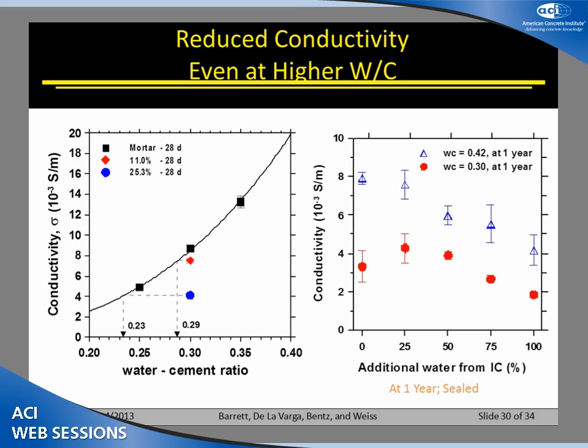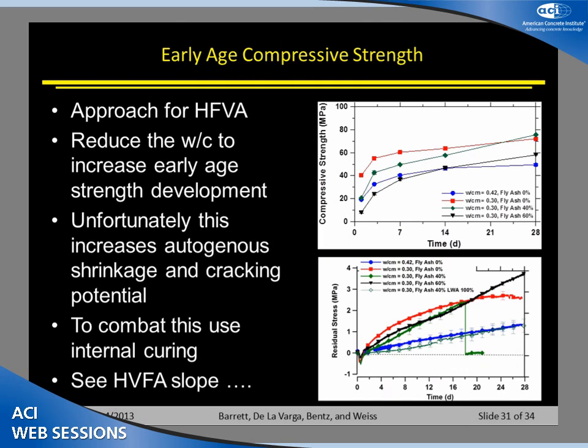All right, but the whole idea here is by internal curing, we have water sticking around for a longer period of time. It's hydrating more of the cement, it's hydrating more of the fly ash, it's densifying the system, so it goes from 8 down to a value that's more like 4. You may say, well, I still don't care if it's 8 or 4 or anything else. This number here is directly related to the speed at which ions move through your concrete. And if you drop that number in half, the ions are moving half as fast. It's going to take them twice as long to get to the reinforcing bar. So you're hydrating more of the system. Very important when you've got fly ash in the system, and this comes from densifying the overall material.